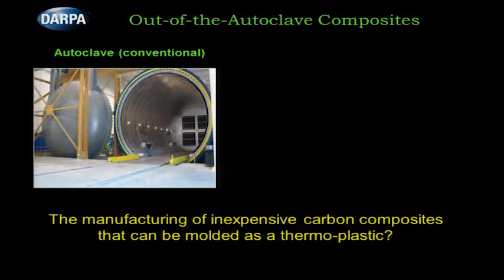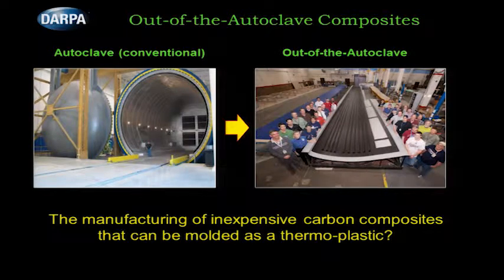So the question is, can you get it out of the autoclave? If you can get it out of the autoclave, very much larger parts can be made at much lower cost than carbon fiber. Now, I also, you see at the bottom here, is it possible to make carbon composites that can be molded like thermoplastics? Well, there's already a hybrid. You make a flat sheet of carbon composite, and you heat it up, and you stamp it. And we make our military helmets this way now.